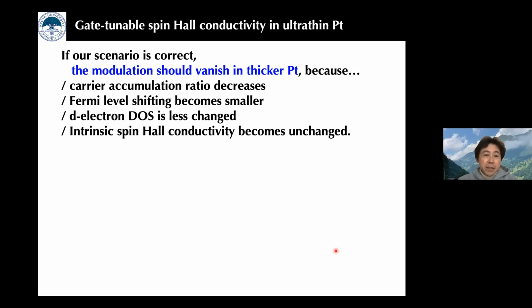If our scenario is completely correct, the modulation should vanish in thicker platinum because the carrier accumulation ratio decreases and the Fermi level shifting becomes smaller, because carrier accumulation does not affect the Fermi level so much. And as I mentioned, the intrinsic spin Hall regime is the key to control the spin Hall conductivity. And in the intrinsic spin Hall regime, interband spin scattering is the key for the spin scattering. This means that the electron density of states around the Fermi level is very important.